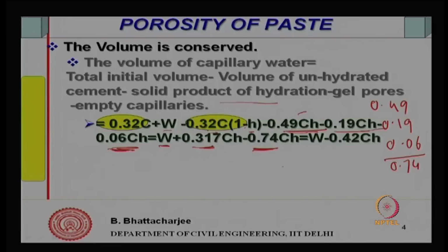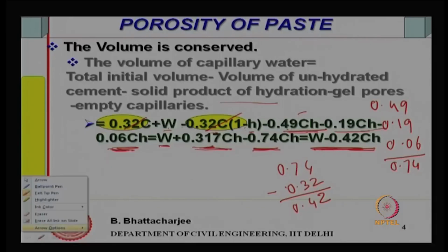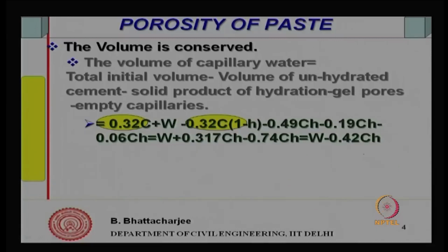And 0.74 minus 0.32 is simply 0.42. So, I get the volume of empty capillaries as W minus 0.42 CH.